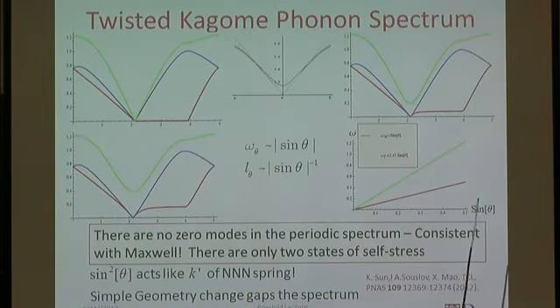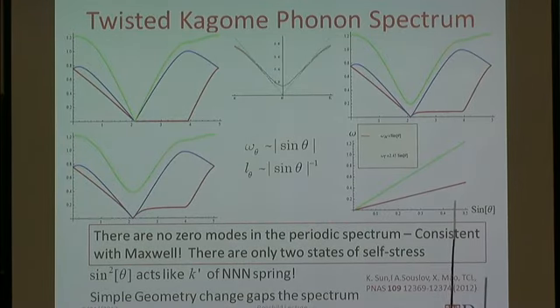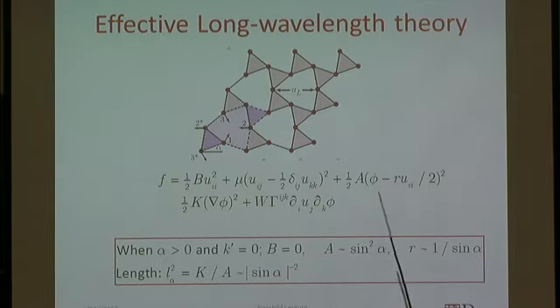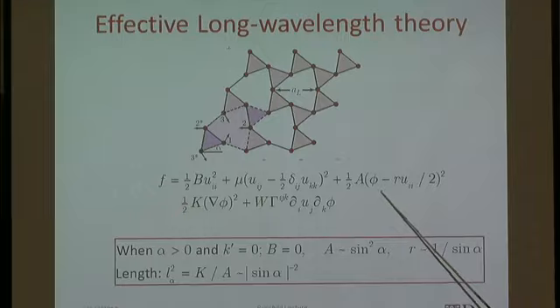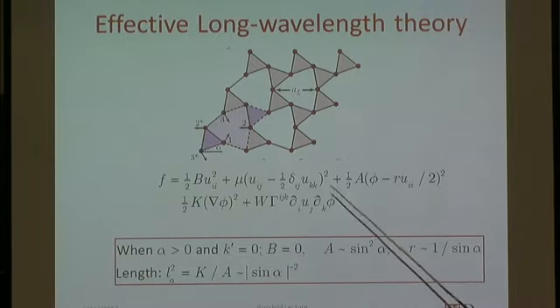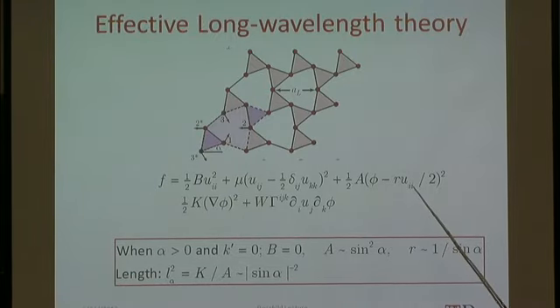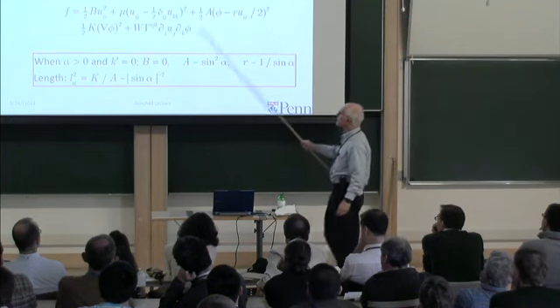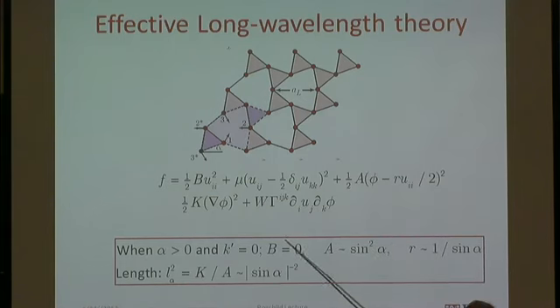So that was a surprise, and it took us a while to understand that. There's actually a nice continuum theory that you can write down that looks a little bit like a gauge theory, where this angle phi tells you how this triangle is compressed, and this is the trace of the strain tensor, which tells you how much isotropic compression you have. So you can see you can have a non-vanishing twisting angle, which changes the size of the hexagon, and that will then drive a compression, and you're left then with, if I set k prime equal to 0,